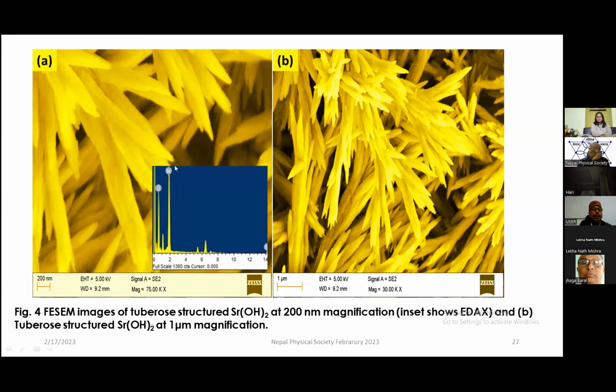The inset shows the chemical composition of the compound, analyzed by EDS, with strong peaks of strontium and oxygen. One can see strontium and oxygen. This guarantees that whatever we have deposited is deposited here, and we get a very good porous structure. So we hope that it will exhibit the supercapacitive property.